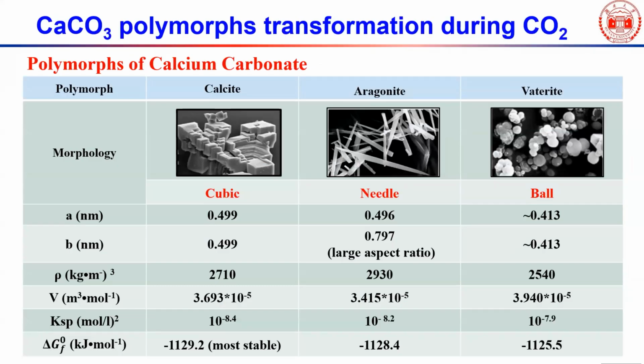And as I mentioned earlier, calcium carbonate has three polymorphs. Crystallized, it has cubic forms. But on the other hand, if you look at the density, calcite is about 2710, aragonite is 2930, and vaterite is about 2540. So they have very different polymorphs and also different densities. During their formation, it will significantly affect the properties of the final carbon mineralized product, because